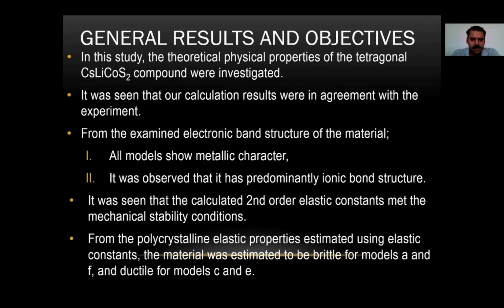It was seen that the calculated second-order elastic constants met the mechanical stability conditions. From the polycrystalline elastic properties estimated using elastic constants, the material was estimated to be brittle for models A and F, and ductile for models C and E.